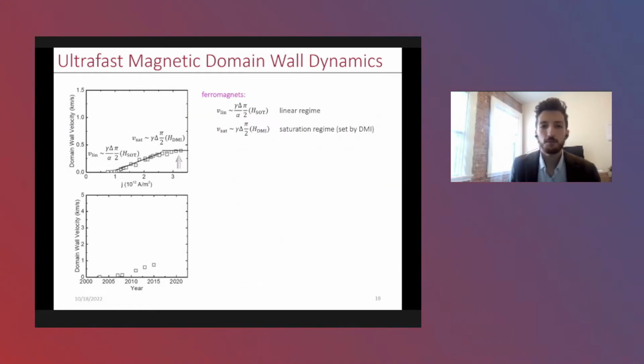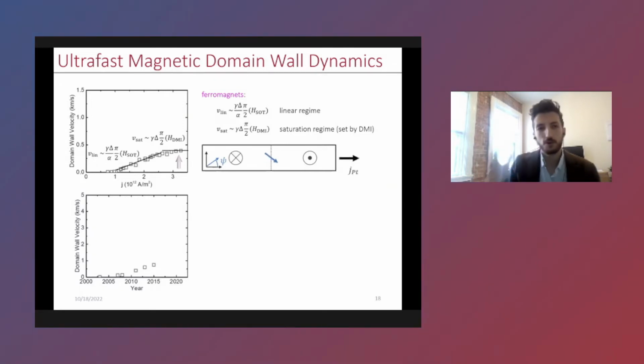It actually comes from the domain wall structure itself, or what the magnetization looks like within the domain wall. In fact, when you drive a domain wall with a spin-orbit torque, not only do you drive it into motion, but you also distort that domain wall towards a Bloch configuration, essentially away from the Néel configuration, which absorbs the torque. So it's not the static structure of the domain wall that's important. It's actually the dynamic structure of the domain wall that's causing this plateau.